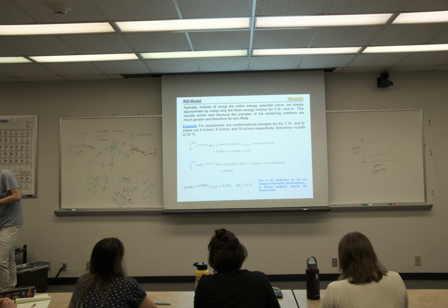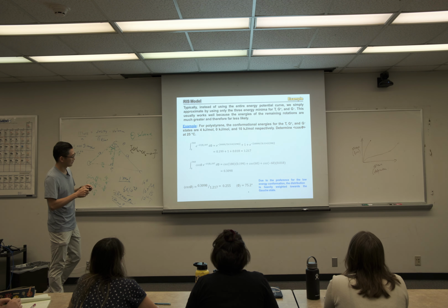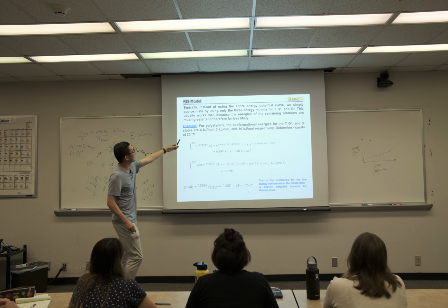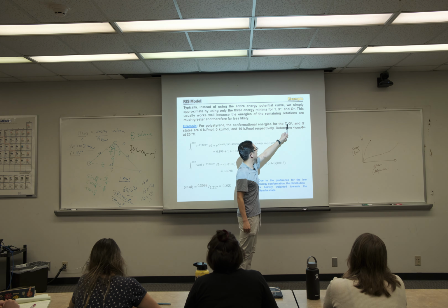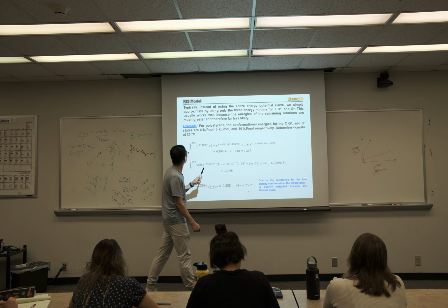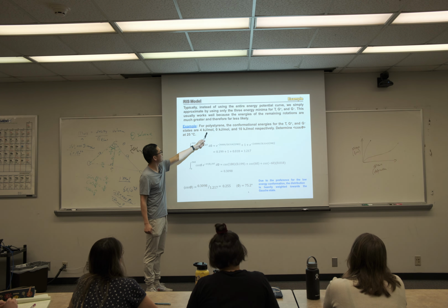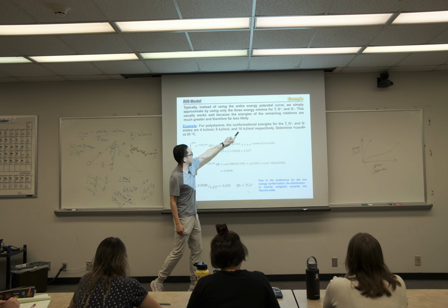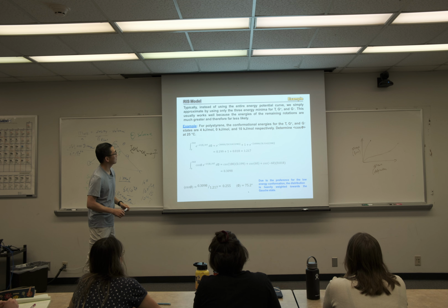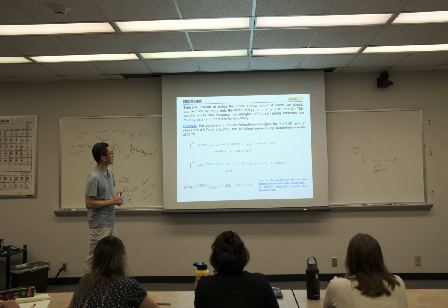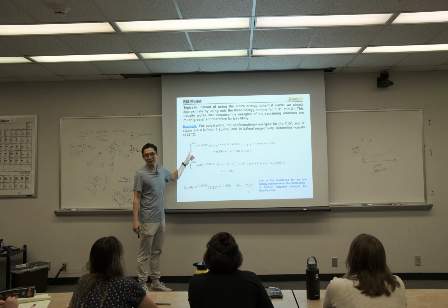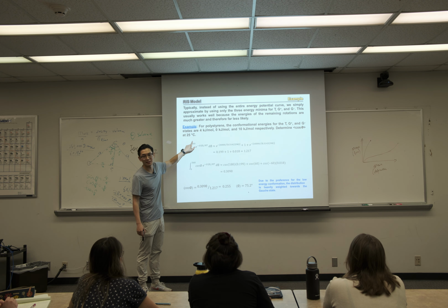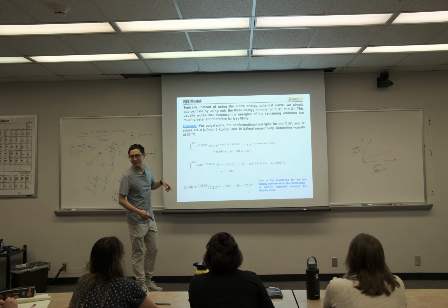This is the only example we're going to show you, and it is for polystyrene. We have conformational energies for trans, gauche plus, and gauche minus of 4 kilojoule per mole, 8, and 10 respectively. So we can determine the average cosine theta. Okay, I need to slow down because I don't think everybody is familiar with this sign. What is this sign? Integral.